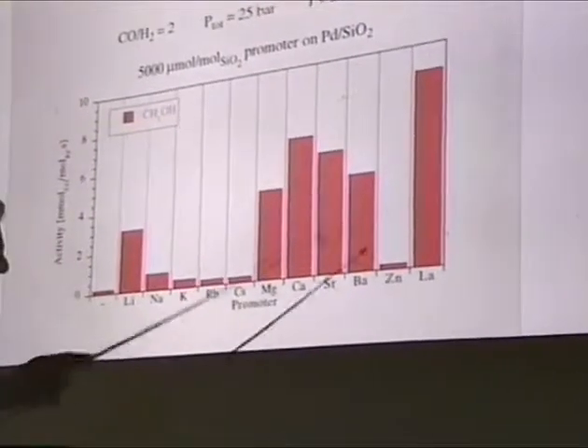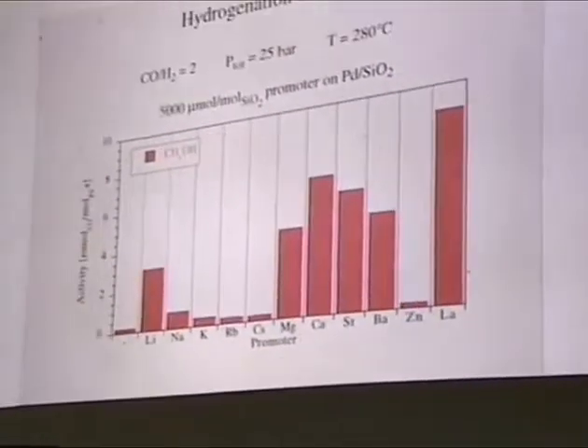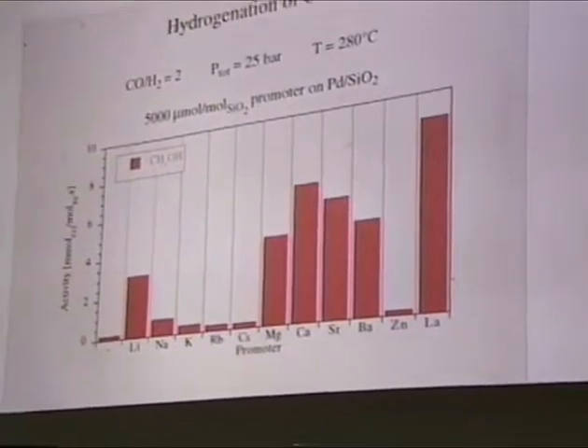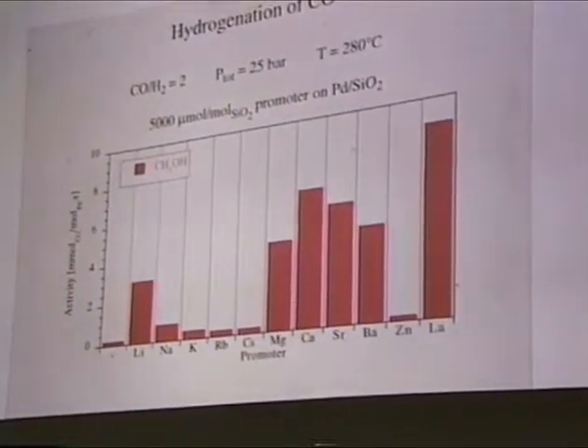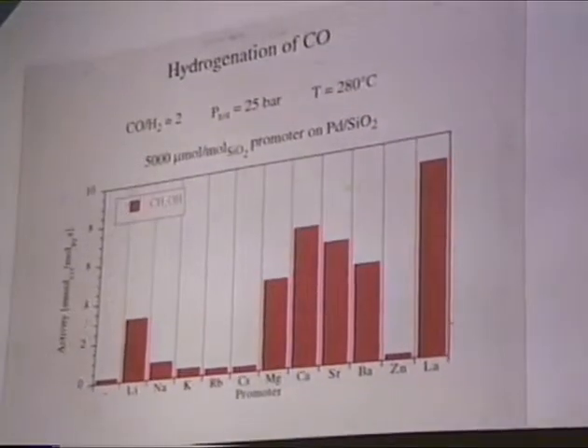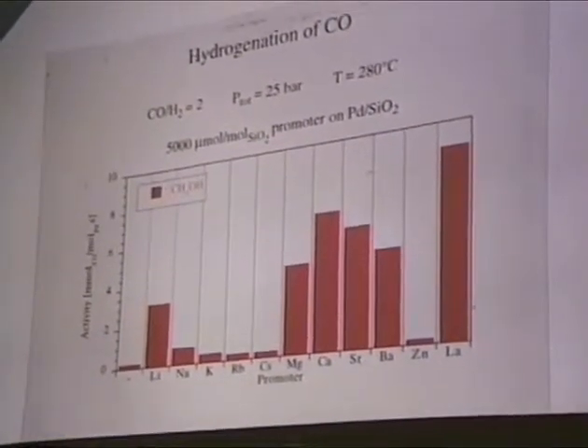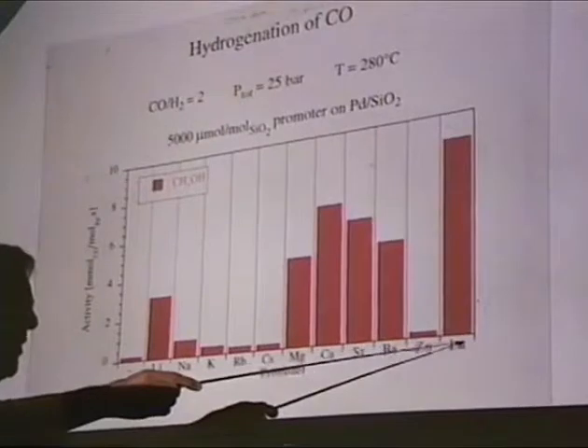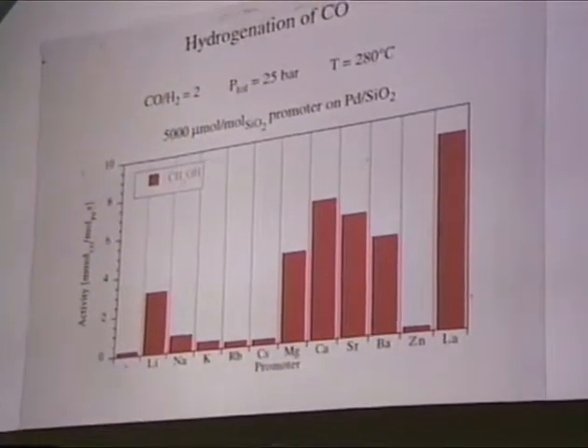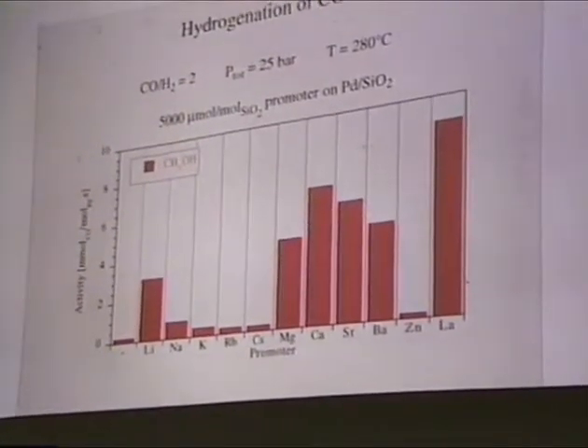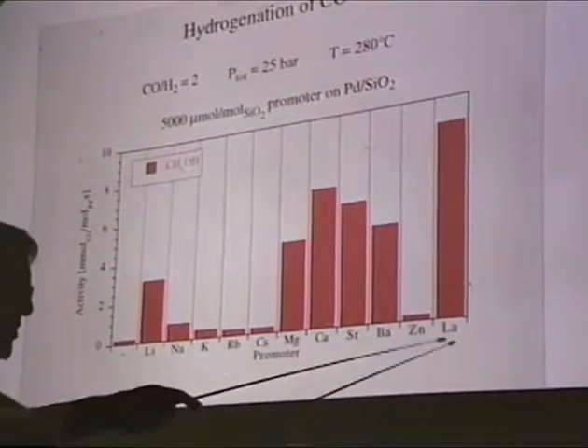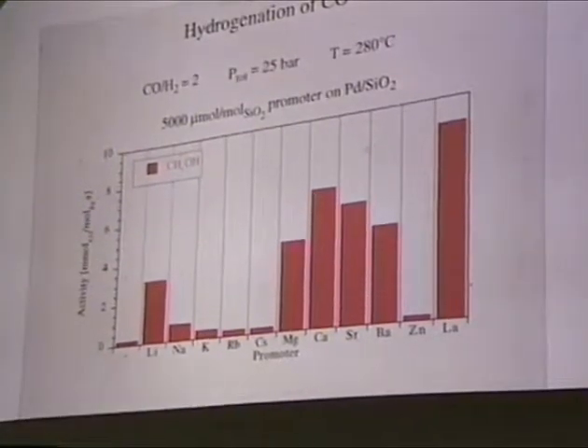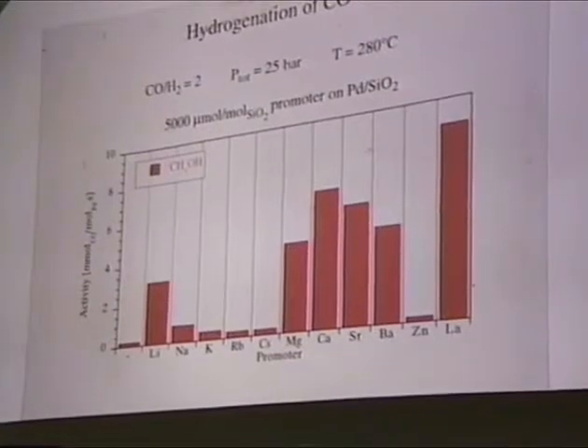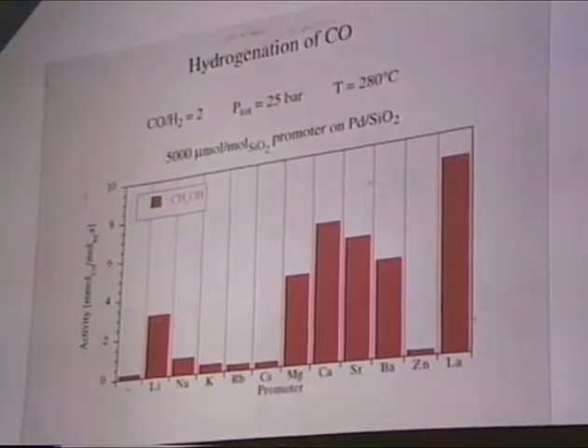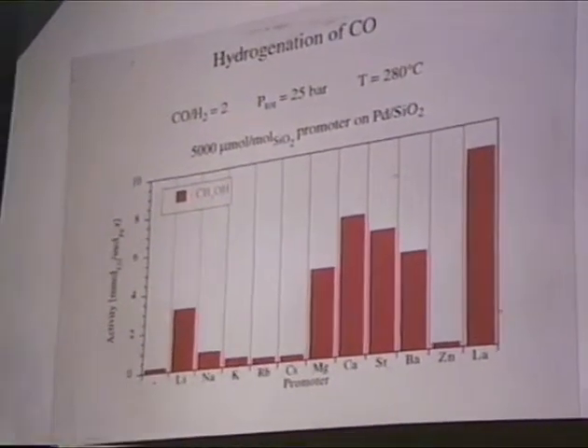You see that the trend here is different. The zinc is very low to our surprise, but don't forget this is not zinc oxide, this is zinc added in this amount on the silica. And then the lanthanum is also very good, but the lanthanum is the exception here because it does make quite a bit of methane. It's the only one which improves even the methane make on the palladium. We have no explanation for that yet. All the others suppress it like I showed for the calcium.